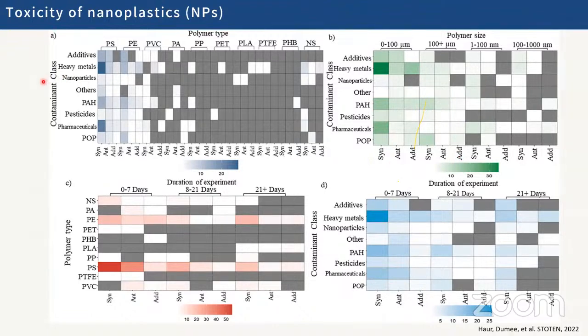Okay, so another thing that has been shown to be occurring is the fact that some pesticides and pharmaceuticals, which are relatively hydrophobic, are able to diffuse, either within the polymers or at least adsorb very strongly onto the surface. These pose other concerns because they can enhance or accelerate the development of bacteria, which are potentially antibiotic resistant and so on, because you are concentrating them over time. So that's a major challenge here.